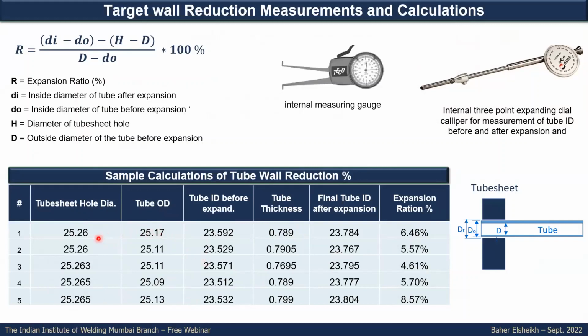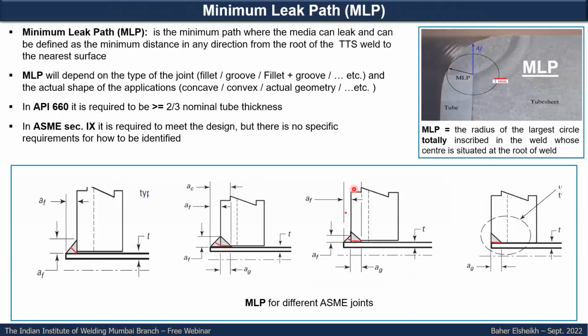Because if you can see here, 0.2 something of a mm will have an impact on the calculated expansion ratio. Then you need to calculate the expansion ratio and compare it with the recommended value, how it should be. Now for the minimum leak path.